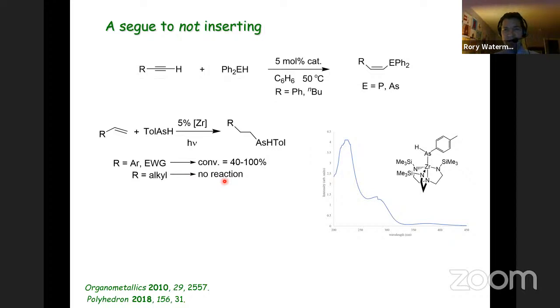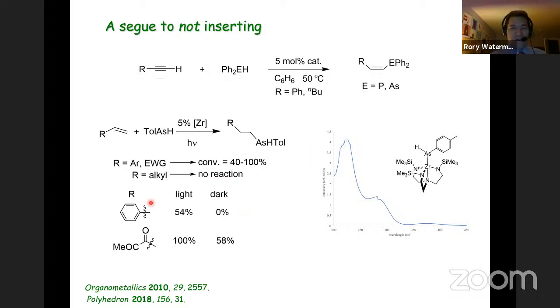And this is arguably a surprising reaction. We would think that the zirconium arsenic bond should be fairly weak. It should certainly be longer. And so there's some reasons to believe that this should be a more facile insertion, even though that's clearly not borne out. But what we did observe is that for the styrene derivatives, we saw only reactivity under photolysis.